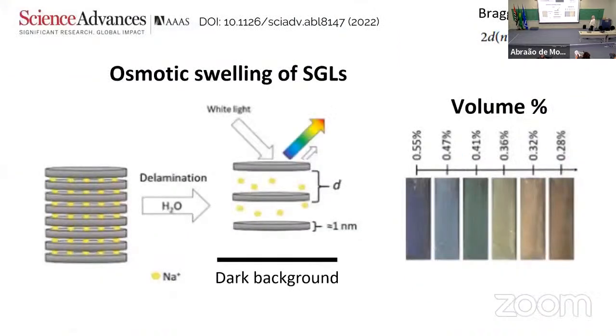So then we tried the same experiment with clays. We took our clay, this time with sodium cations in here. We delaminated in water. We shine white light on it, and we look at the light coming back. And you see some tendency of coloration. Not very impressive. We call this mediocre colors. It's nothing we would publish. But then we did a trick.